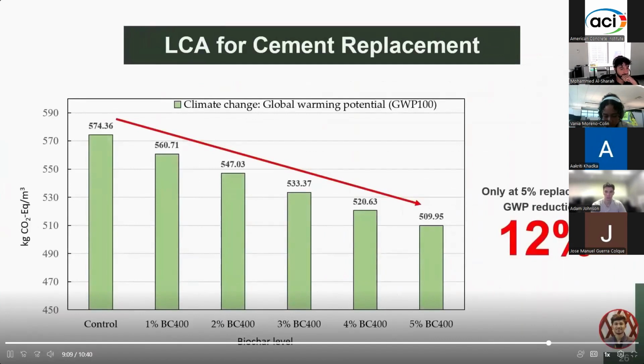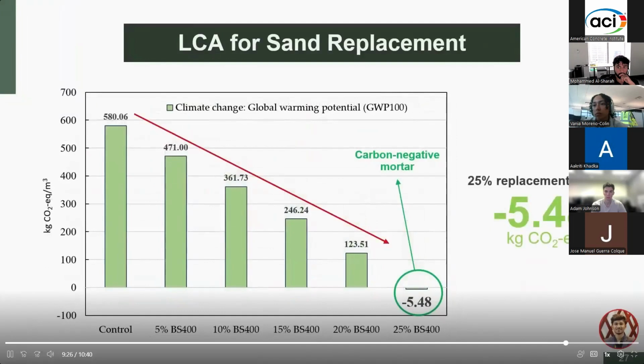When we incorporate biochar at various levels, the emissions decrease gradually. At only 5%, the global warming potential reduction is more than 12%. It is a huge improvement for our climate condition. On the other hand, for sand replacement, the reduction of global warming potential is far more than cement due to the higher quantity of biochar. As you can see, at 25% replacement, we achieved a carbon negative cement mortar, supporting our core objective.